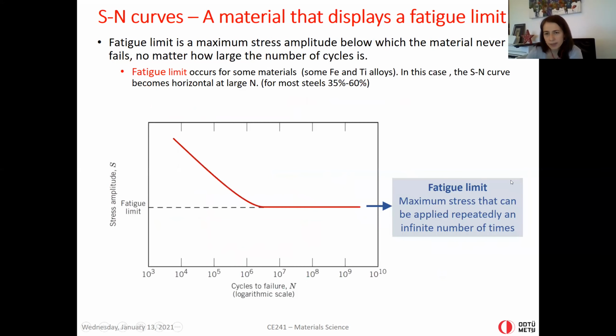But some materials display a fatigue limit. It is the maximum stress amplitude below which the material never fails, no matter how large the number of cycles is. Fatigue limit occurs for some ferrous and titanium alloys. In these cases, the S-N curve becomes horizontal at a large number of repetitions. For most steels, this value is around 35% to 60% of the tensile strength. And fatigue limit is basically the maximum stress that can be applied repeatedly an infinite number of times. To briefly summarize, here on this graph, you can see the horizontal portion at large N. This is your fatigue limit.